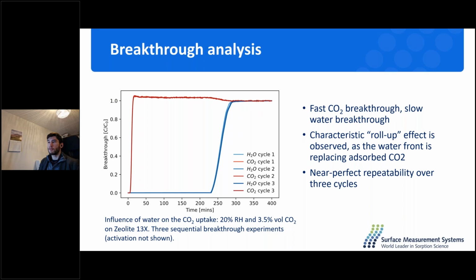So one needs to be very careful when integrating these curves to find out the amount adsorbed, that they integrate this part at the start, but also this negative CO2 that is being displaced. So all of this curve has to be integrated in order to obtain an accurate amount of CO2 adsorbed. If we stop here, it is not going to be a correct picture.